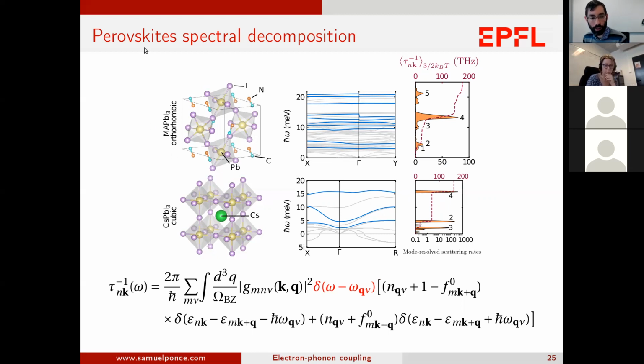In particular, cubic MAPI is very difficult to simulate because the molecule will have many configurations. You have the stochastic motion. Exactly. So I think the proper way, but this would be very expensive, would be to do all the directions, then do the calculation for each direction, and then do a thermodynamical average of the result along all of those. But the problem is that for each of those,